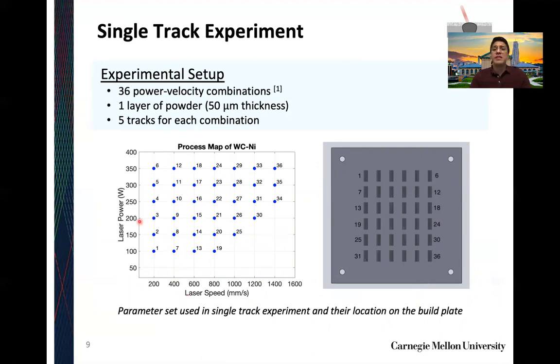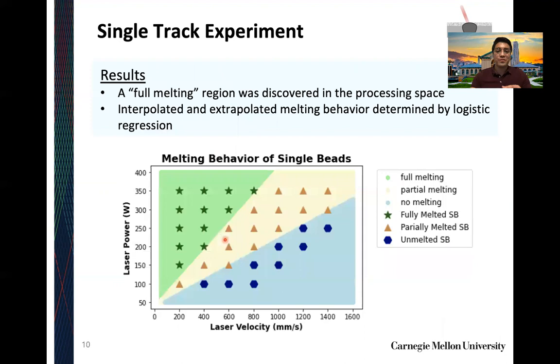Now, the way we got these power velocity combinations, which you see here, where the y-axis is the laser power and the x-axis is the laser speed or velocity, was by referencing a previous experiment done on the single tracks or single beads of a nickel alloy. So we were essentially replicating an experiment done on a pure nickel alloy as compared to what we're doing now, which is a nickel alloy with 80% tungsten carbide in it. And it was quite exciting to see that we got very close to similar results.